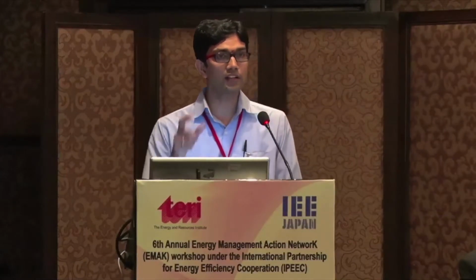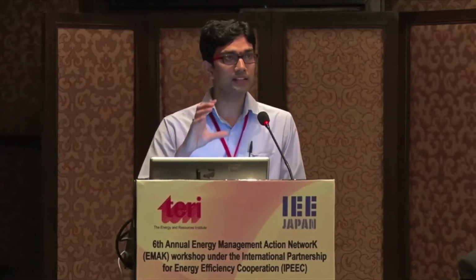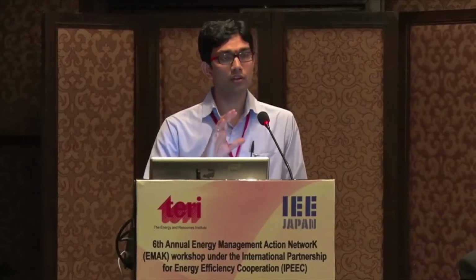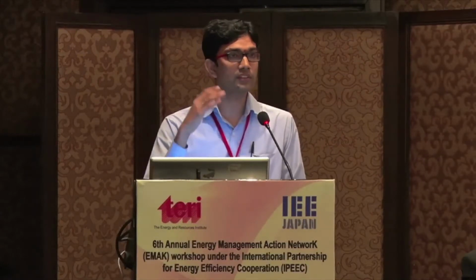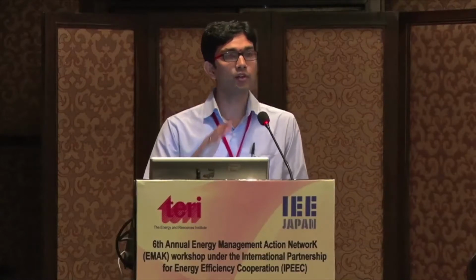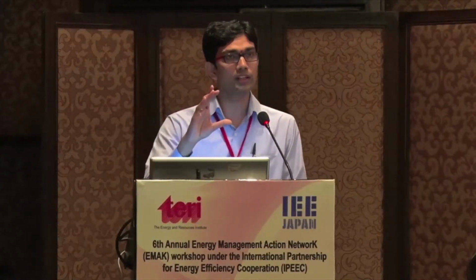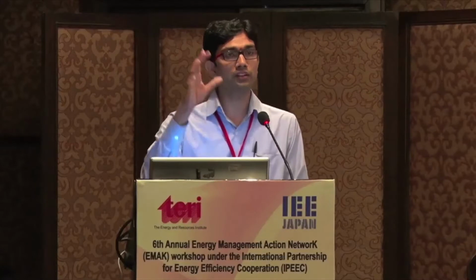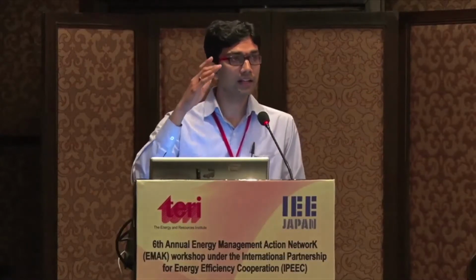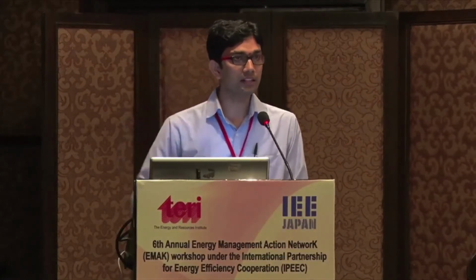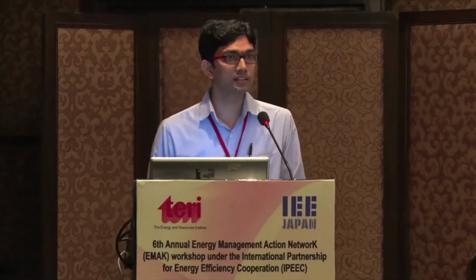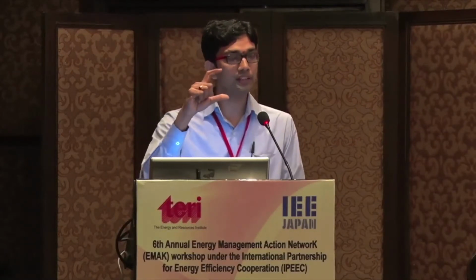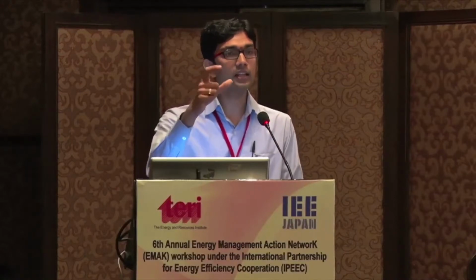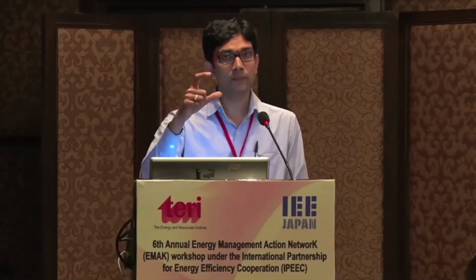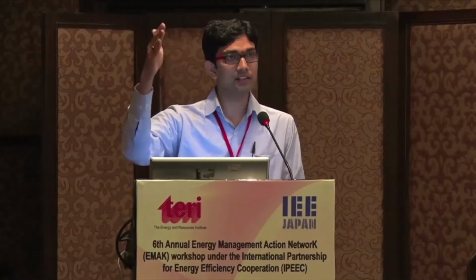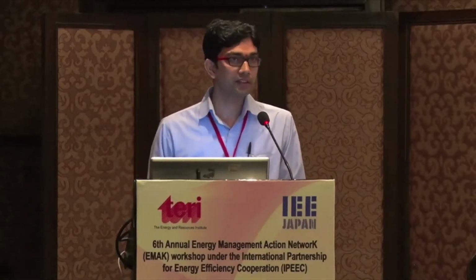In other words, if we reduce the quantity of air that is going in at ambient, which is over and above the actual requirement, we are for no reason increasing that quantity of air from 30 degrees centigrade to 1100 degrees centigrade, and again leaving it at 900 degrees centigrade to the atmosphere from the flue gas. So the fuel that is going in heating that incremental air volume to raise it to that delta temperature can be saved with the help of